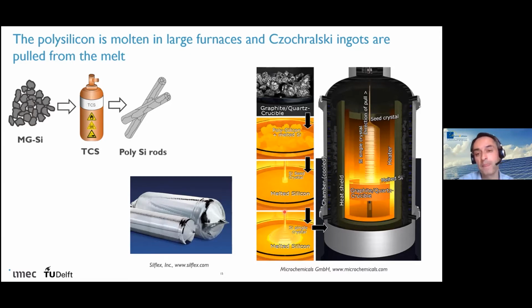What happens then is this molten silicon is sort of attracted, also goes upwards, starts to cool down, and starts to crystallize, taking on the same crystalline structure as this silicon seed layer. So in this way, we can slowly pull a cylindrical ingot from this melt. It looks a little bit almost like a magical process, but it works really well.